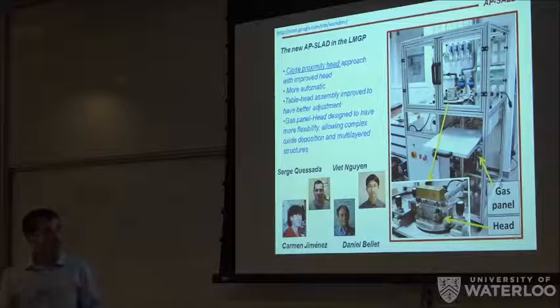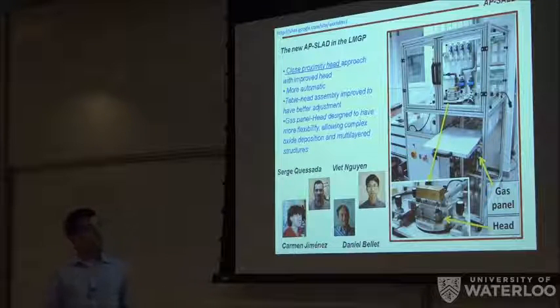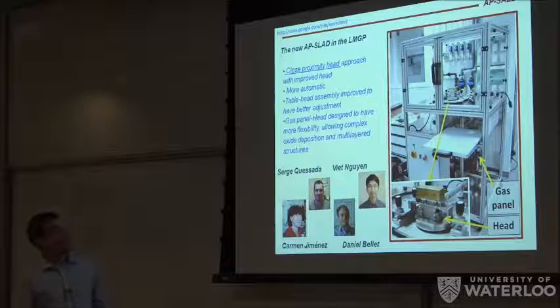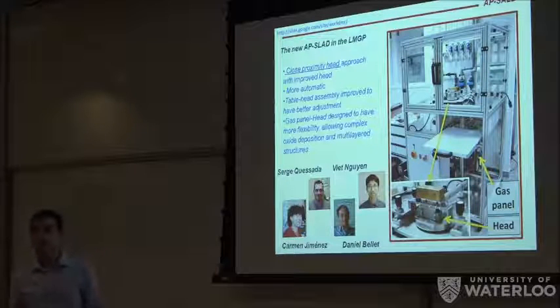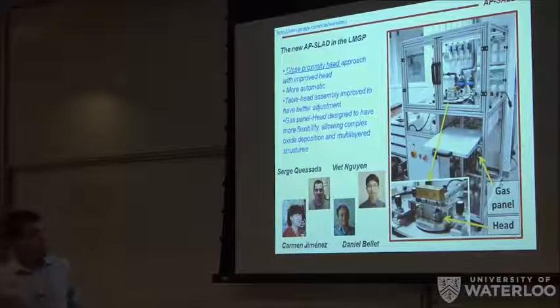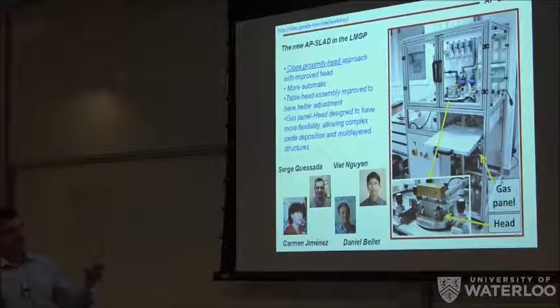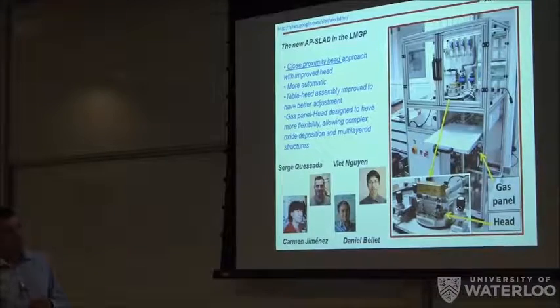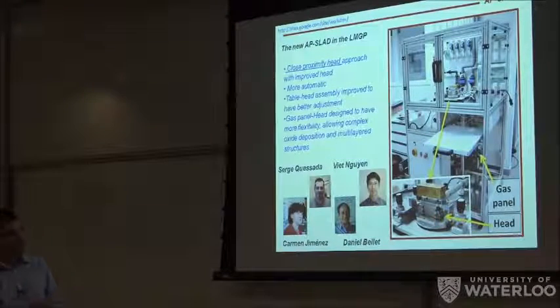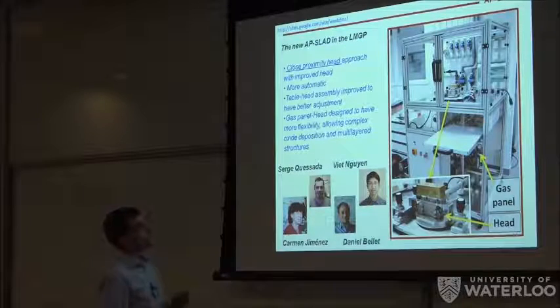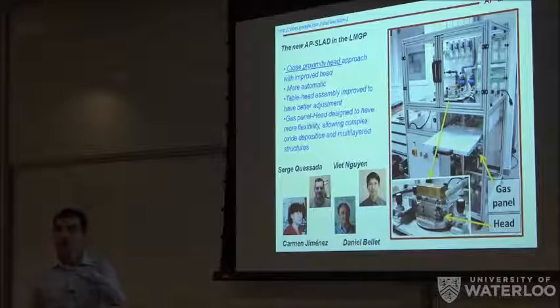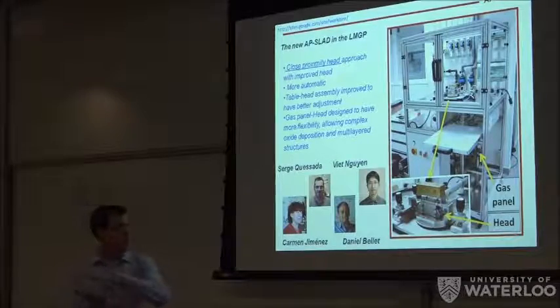This is the system we have developed now in the laboratory in France after I got there, and it's very similar to the approach followed by Kodak. So the main piece is the head, where we managed to distribute the different flows in parallel channels, and the rest is just the gas panel, the electric control, the valves, but it all happens here. You have the sample in the substrate, which is going to scan back and forth under the head, and we are trying to make a better adjustment of head and substrate, because it's very important to have a parallel alignment and a very controlled gap distance so that you will be homogeneous and reproducible. So that's what we are working on.